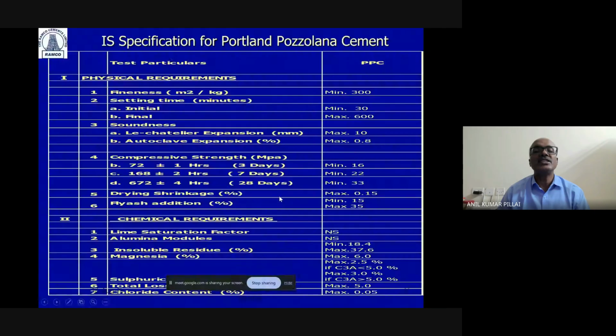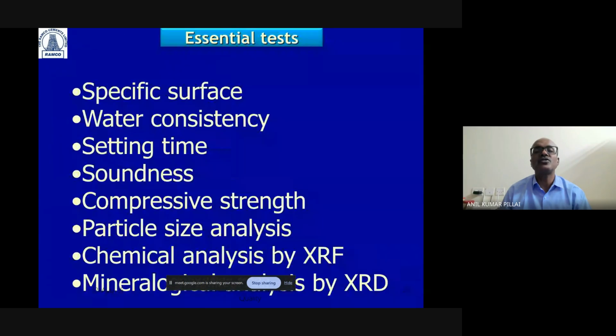And here you will find drying shrinkage is also measured, and the fly ash addition is there. For example, in the cement manufacturing process, the minimum limit is 15 and the maximum is 35%. Now this limit is not there when you add fly ash at site. You can go in for a higher percentage, but this limit is only applicable in the case of cement manufacturers. So here you will find the insoluble residue. In fact, this is just a representative value. But there is a formula for insoluble residue in terms of the fly ash percentage: if the fly ash percentage is higher, your insoluble residue will also be higher.